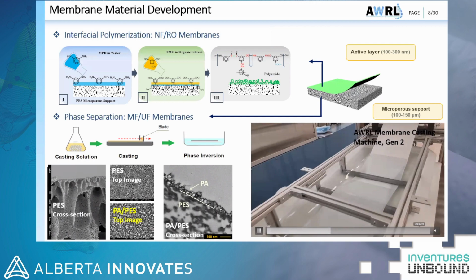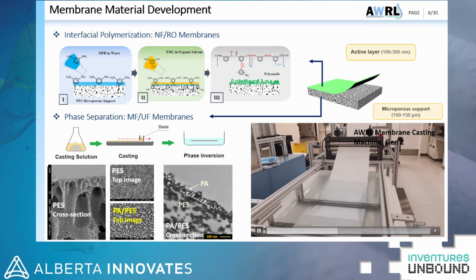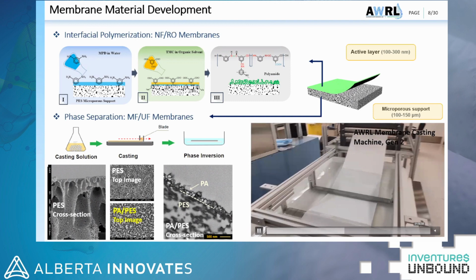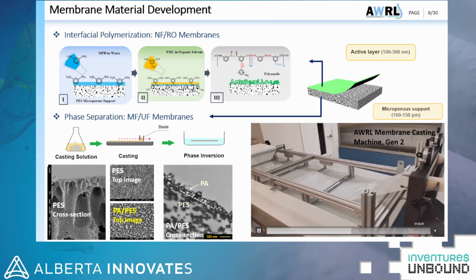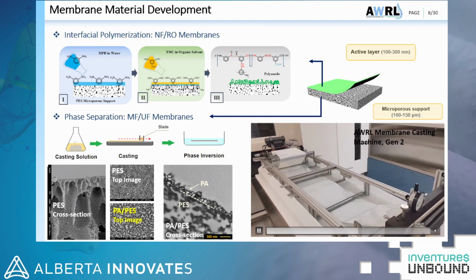Then we apply interfacial polymerization reaction to coat a very thin layer of polyamide on this porous membrane. In interfacial polymerization, two monomers, MPD, m-phenylenediamine, and TMC, trimesoyl chloride, react with each other at the surface of the porous membrane that we just created.